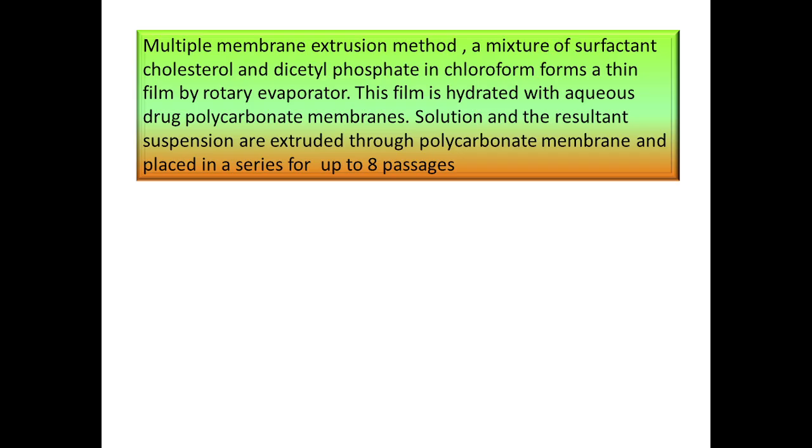After that, multiple membrane extrusion method. A mixture of surfactant, cholesterol and dicetyl phosphate in chloroform forms a thin film by rotary evaporator. That film is hydrated with aqueous drug solution, and the resultant suspension is extruded through polycarbonate membranes placed in series up to 8 passages.